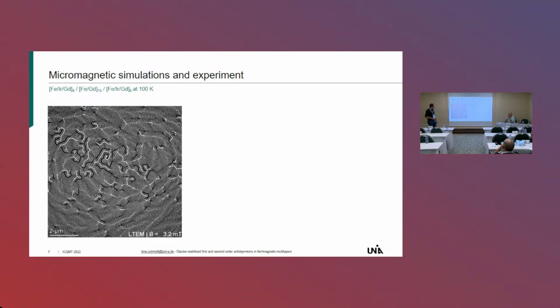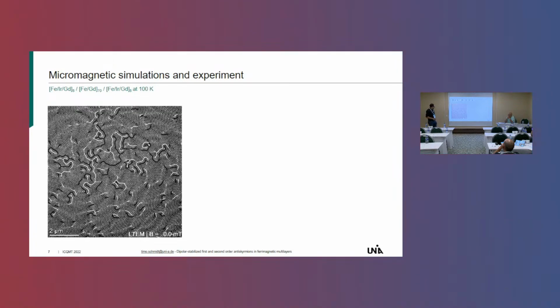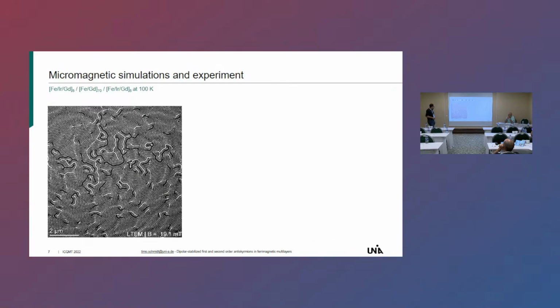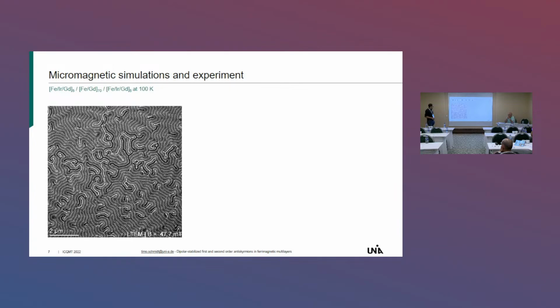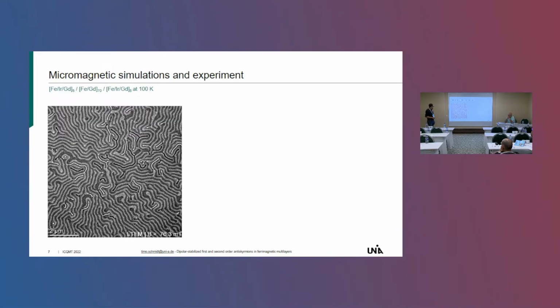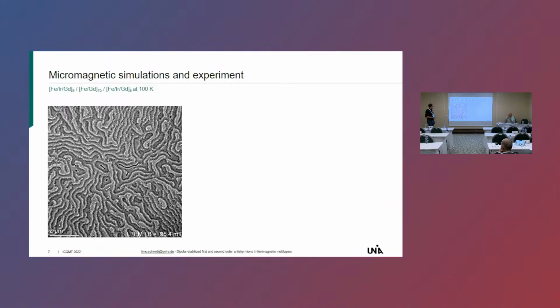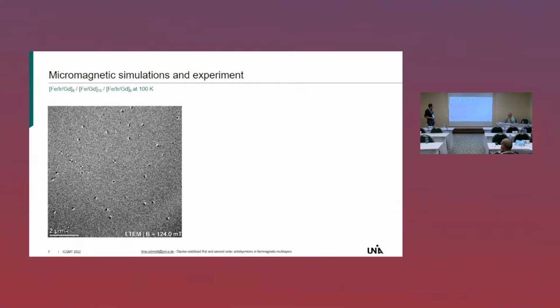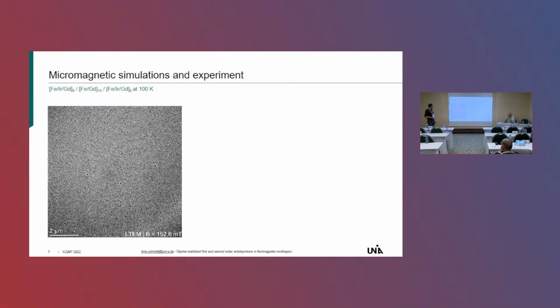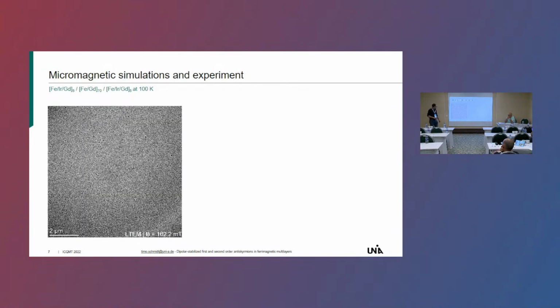And I also brought you a little film to see it with your own eyes. So we increase the magnetic field, and you see that the domains get bigger, and there are some Skyrmions here, here, here, and now everything breaks up into bubbles. The bubbles disappear. There were anti-Skyrmions for a second, but I couldn't talk fast enough. And after that, we are in this situation, and everything annihilates. The picture is shifting a little bit. That is because if you excite the system with a magnetic field in the Lorentz STEM, the beam also gets a little bit shifted.